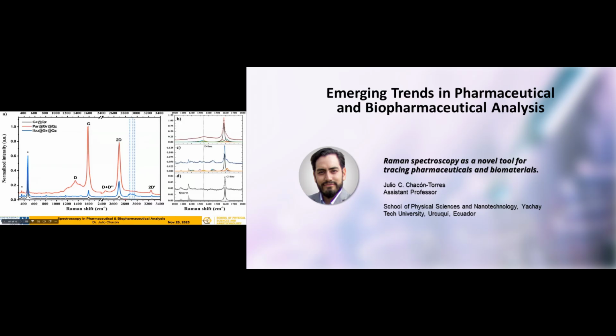So what we did was a deconvolution analysis of the Raman spectra, first of the pristine graphene G line. We notice some of the peaks of quartz because it's underneath the graphene, and the G line is clean, nothing else. But after we deposited the ibuprofen, we noticed that there were some additional peaks, and also on the paracetamol. And these additional tiny peaks were related to the presence of the molecular vibrations of our pharmaceutical. We compared the positions of those peaks to the ones of the pristine material, and we confirmed that indeed they belong to this molecular structure.